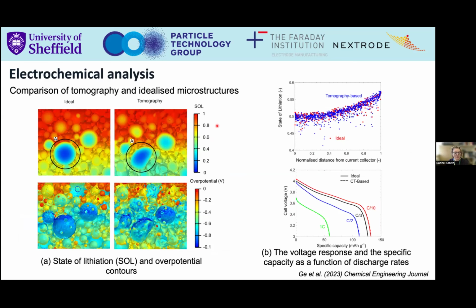So we wanted to double check, because we're taking a tomographic scan and turning that into spheres, we wanted to check, okay, how does that change the state of lithiation or voltage, for example, in an electrode? So we took out these ones here on the right are our tomographic scans, and then on the left we have our ideal or our spherical scans, basically our spherical approximations. And what we wanted to do was look at, when we run our simulations of the electrochemical performance, how does that affect the performance that we're getting?